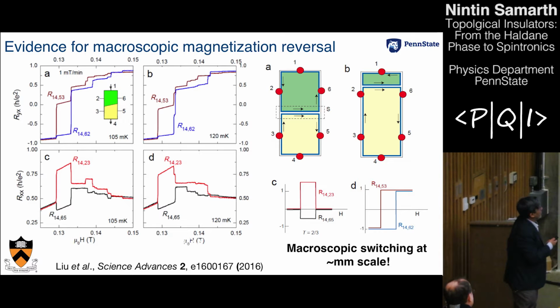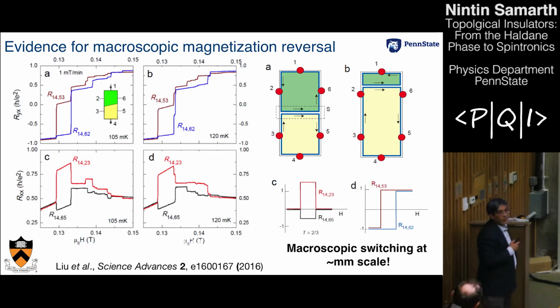Similarly, if you measure this voltage and this voltage simultaneously, then you find that one of these voltages jumps up and the other voltage jumps down at the same time. Now, this is rather odd, and the only way that we can explain it is by using a simple model. It's a Landauer-Büttiker model in which we imagine that there is a very simple structured domain wall that's sweeping across the sample. And here are the results of this modeling.